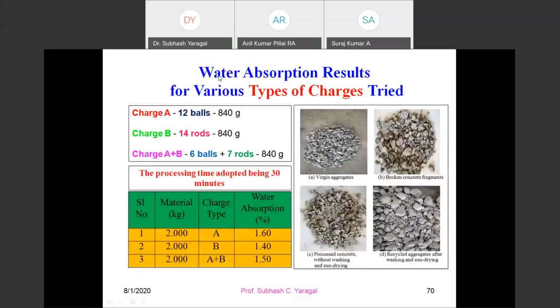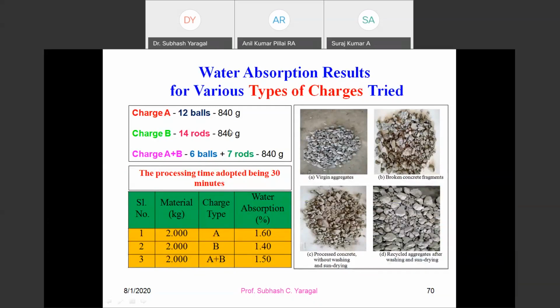Next, water absorption results for different types of charges. We have tried, this is what I have reported, only rods. The charge weight is about this. Conventionally, people have used steel balls like in the ordinary Los Angeles machine in the lab. They have used steel balls. We have used the combination. Our study showed that using a rod mill, you get the best processing here. Charge A is the ball mill, and A plus B is both the ball mill and rod mill. So we have optimized the rods as better.